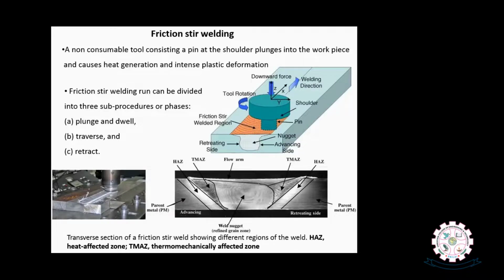Whereas in friction stir welding, you can see the stir zone where the material does not undergo melting. However, within the solid state itself, the material will be subjected to plastic deformation, and a perfect metallurgical continuity between the two metal surfaces can be achieved at the interface. Usually it contains a nugget zone and a thermomechanically affected zone and a heat affected zone, and then adjacent to that the base materials, as shown in this cross section of the friction stir welded alloy.